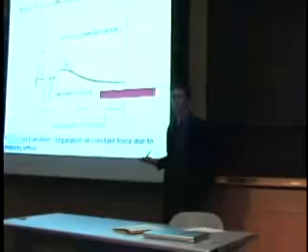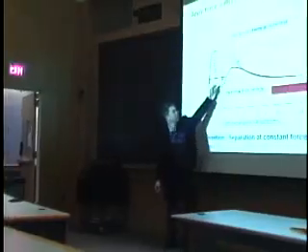And then you pull the saturated crack apart. Essentially, because you've done your thermodynamics right, you actually have a first order transition in length space. This is a length discontinuity, just like a volume discontinuity in a regular first order transition. Here the crack is separating at constant force.